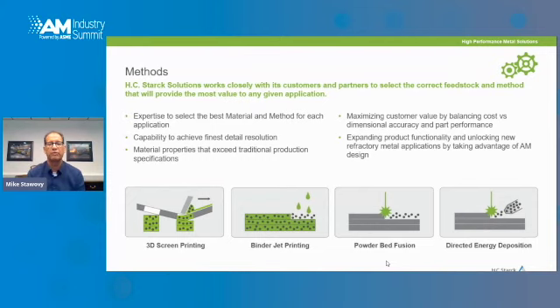If we talk about the methods that we've tested within HC Starck, we've focused on 4 main areas for making metal parts. We have a technique called 3D screen printing that we've worked closely with partners on to develop for printing vertical structures, vertical grid structures. We've done quite a bit of work with binder jet printing where that makes sense with refractory metals. Powder bed fusion is obviously the most common AM technique, and we've applied that where we think it makes sense for refractory metal materials. And then directed energy deposition, looking at both powder feed and wire feed techniques.